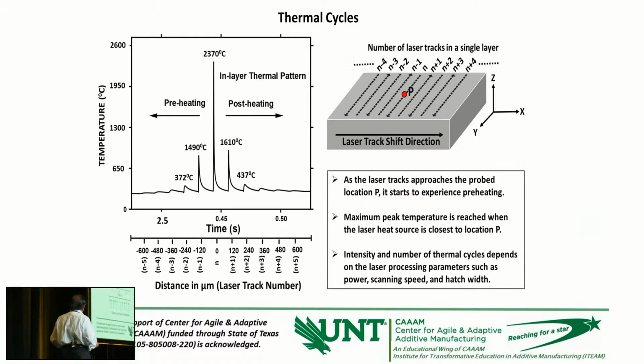So this is how one layer is shown. These are the tracks made in one layer. In the model, we put the electronic probe at one location, and then the tracks are made. Our computational probe is here, which starts looking at the development of the temperature around it. So this is the first track, second track, third track, and the fourth track gets made, and then the fifth track passes this location, and the probe continues to monitor the temperature, and that is plotted here.